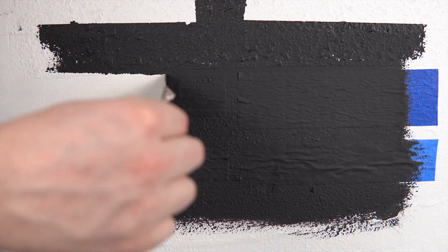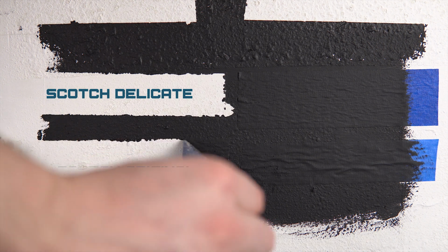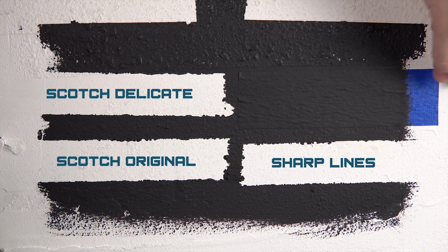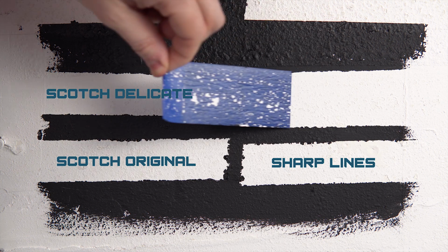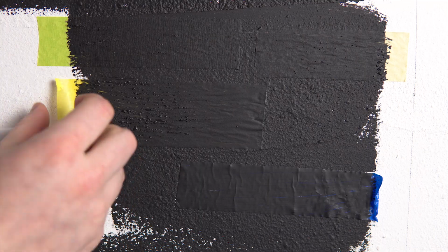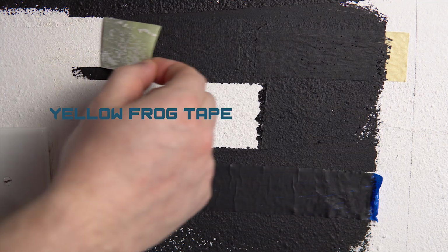The 4 tapes did not appear to change much from being outside, aside from ripping off the paint from the wall as expected. This is why you should always remove your tape as soon as possible. The rough surface actually performed decently in this test.